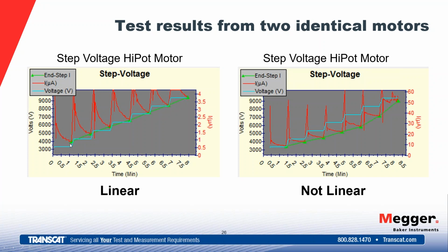What we're reading again is current. So we're going to take a current reading at the end of that one minute, and then we're going to ramp and raise voltage up again by the same amount each step. We're going to hold for the same amount of time for each step, and then we're going to collect the current value at the end of each one of those steps. So what we expect here is that as voltage changes, current will change, but it should change in the same way. If we're raising voltage the same amount, our current should change the same way.